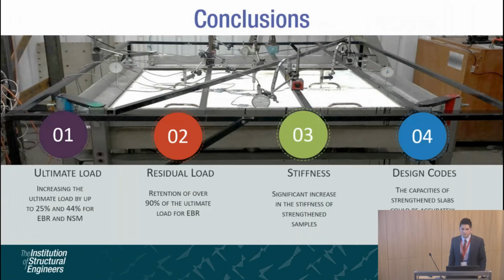To sum up, both methods, EBR and NSM, could be used to increase the ultimate load. The average load increase was 25% and 44% for EBR and NSM. With the EBR system, we are retaining up to 90% of its residual load, which is basically the drop in the ultimate load deflection curve. All of the samples displayed a very high level of stiffness, and by modification of the code and introducing new terms into the design code, we can actually predict the capacity of strengthened samples.